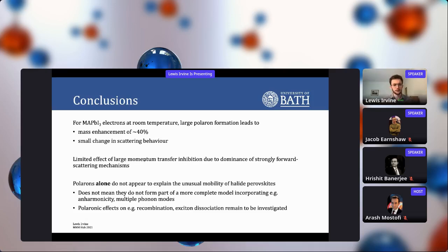And then finally, polarons alone don't appear to explain the unusual mobility of halide perovskites. That doesn't mean that they don't exist, or that it's not the appropriate theory to use, but it means that they have to form part of a more complete model. Looking at the literature, things have been suggested such as anharmonicity, multiple phonon modes or dynamic disorder. So they should be considered within the framework of that.